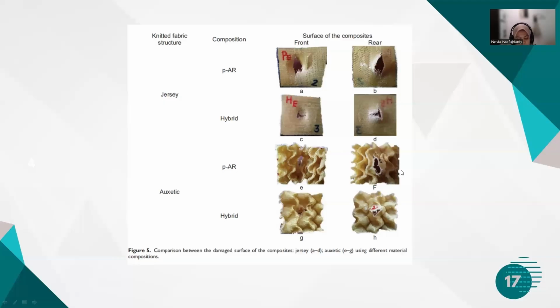This morphological characteristic agrees that the influence of the rupture of the interface on the failure of a composite under impact arises from the middle surface to the tension side of the composite, to the rear surface. For the hybrid composite, the front and rear side have a rounded dome aspect, indicating a more homogeneous deformation. And this failure type is indicative of matrix crushing.